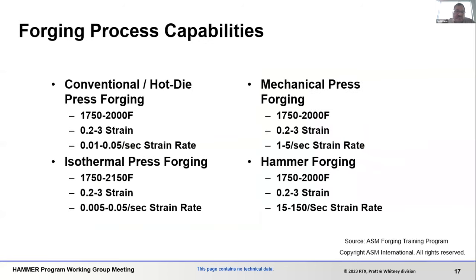So one of the things to think about for forging processes in conventional and hot die forging approaches: the temperatures, again, are in different ranges. They may even be a little bit lower than that. They can be room temperature up to a couple thousand degrees. Strains, 0.2 to 3 true strain. Strain rates can be low in hydraulic presses. Isothermal forging, again, can be done at very high temperatures, strains very high, strain rates typically very, very low. And again, for the purposes of superplastic forming.